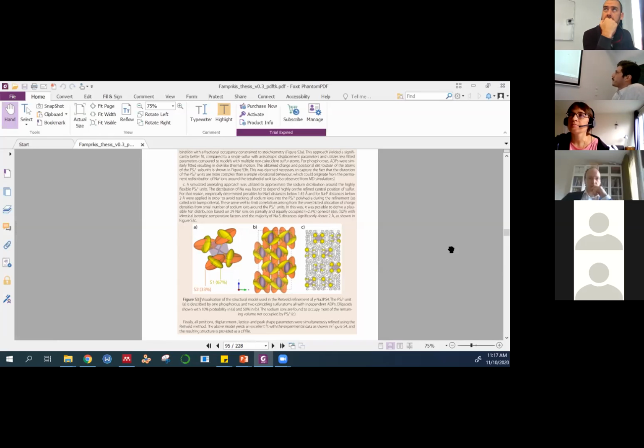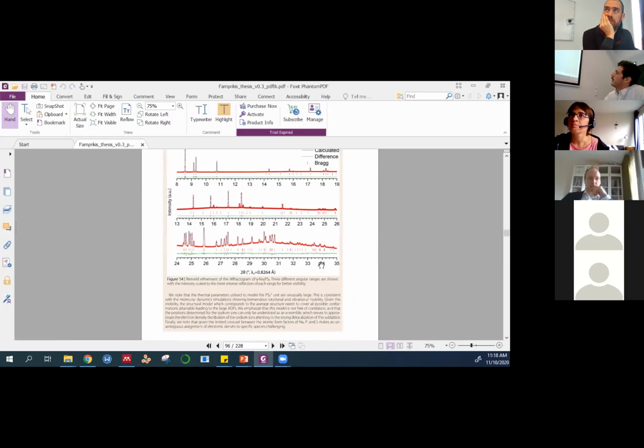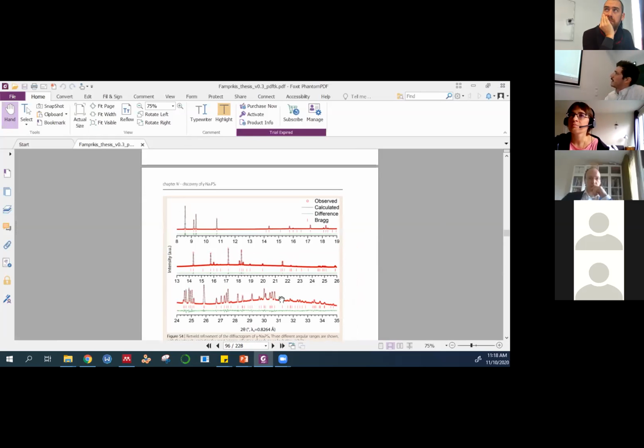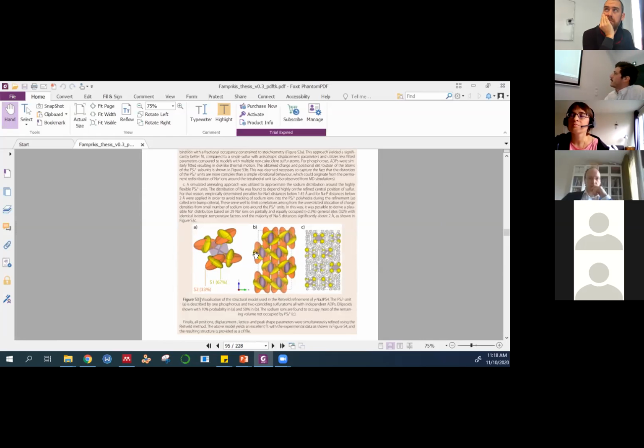Anyway, indeed, we can fit all parameters in the end at the same time. Indeed, this is a bit of an overextension compared to the amount of peaks that we have. The reason why, in general, I did not want to put too much weight behind this Rietveld solution is exactly because, with no offense to anyone, I don't think that Bragg diffraction is a method that is particularly suited to describe such a structure. If you just look here, the solution actually shows very good agreement between the data and the calculation, but what does it actually tell you?